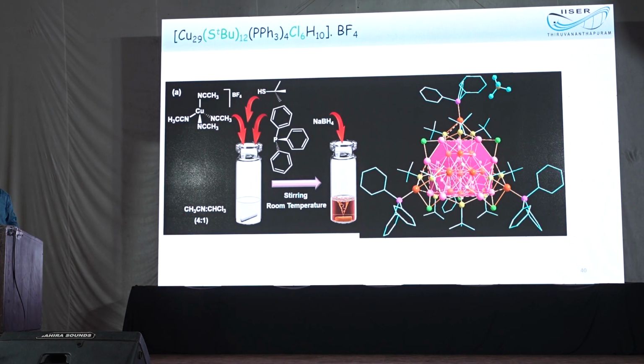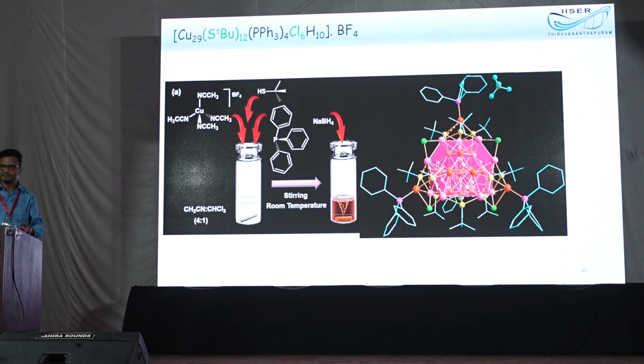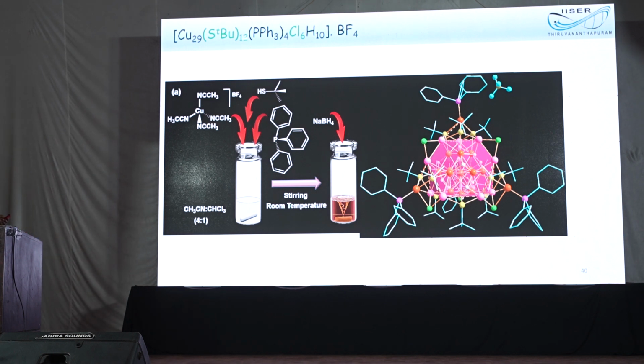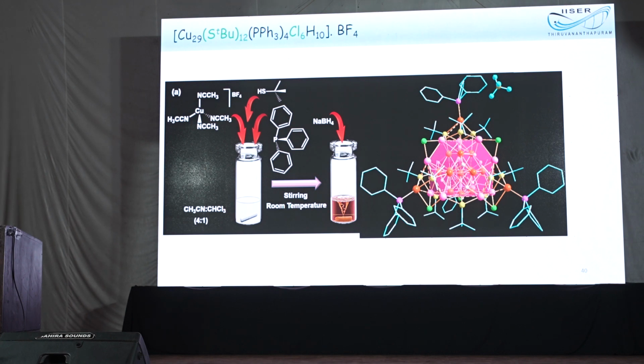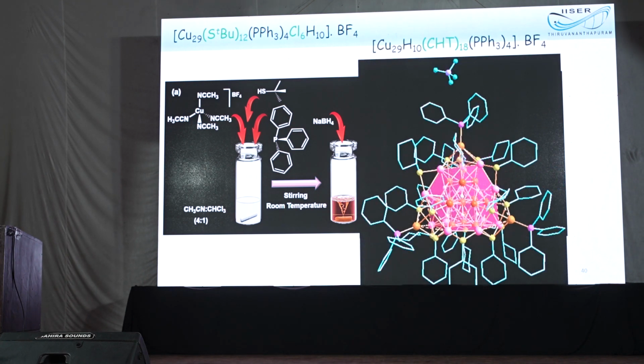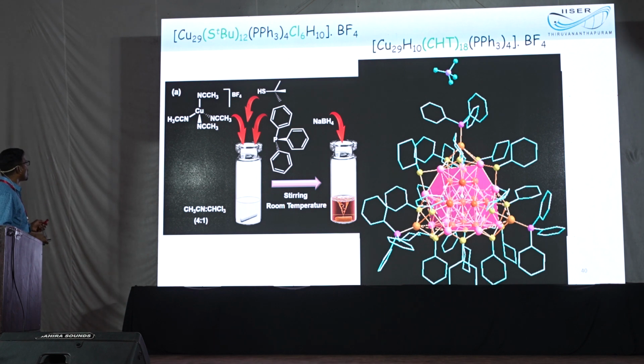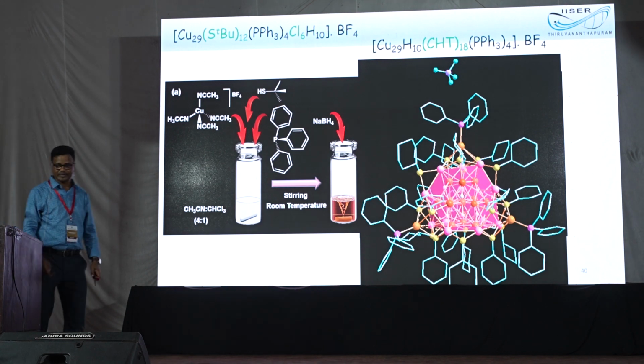We have synthesized a copper 29 cluster. The copper 29 cluster has tertiary butyl thiol and chlorine, protected by triphenyl phosphine. Then I replaced the tertiary butyl thiol with cyclohexanethiol, and we can see that we got an identical structure. Everything is the same, the hydride number is the same. Only the tertiary butyl thiol 12 and chlorine 6 are replaced by the cyclohexanethiol.